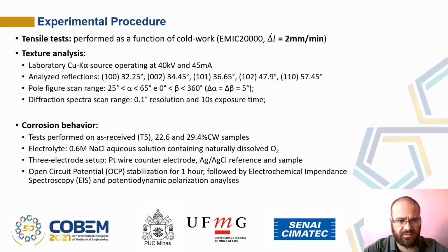The corrosion behavior of the materials was analyzed in selected conditions, which were the as received T5 condition, and the 22.6 and the 29.4 cold worked samples. All tests were performed in a 0.6 molar sodium chloride solution containing naturally dissolved oxygen, and a conventional three electrode setup was used with platinum wire counter electrode, silver chloride reference, and the sample itself. In each case, the following techniques were employed: open circuit potential stabilization for 1 hour, followed by electrochemical impedance spectroscopy and potentiodynamic polarization.